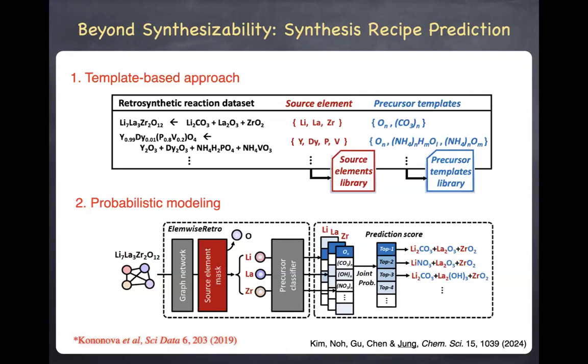But those generative models can actually sometimes, quite oftentimes, yield very unrealistic compounds. And so instead, we formulated this inorganic retrosynthesis as a template-based approach. That was motivated by the fact that if you look at the inorganic synthesis database, unlike organic synthesis, where you can choose reactants from millions of different kinds of organic compounds, for inorganic synthesis, oftentimes people use the same precursors over and over again.